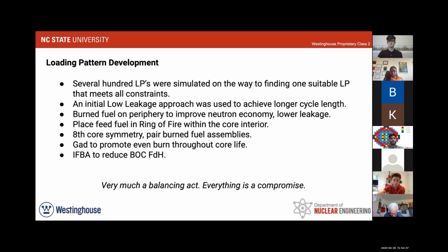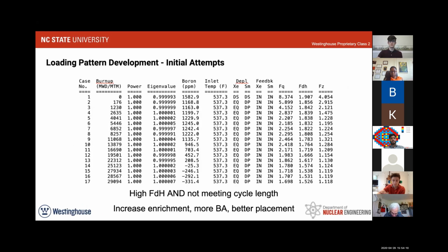Next slide, please. This is one of our initial attempts. As you can see in the boron section, at the end of it, you had a 331, which is definitely not any kind of cycle length requirement that we had. And if you look in the FDH section, you see the first case had a 1.9 FDH, which is way above our constraint of 1.55. And so in order to work on this, we had to increase our enrichment, add more burnable absorbers, and have a better placement of our feed fuel assemblies in the reactor core.